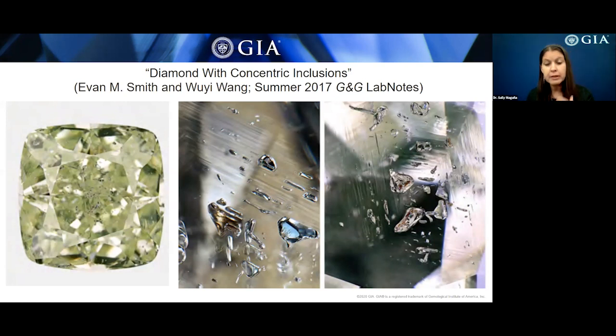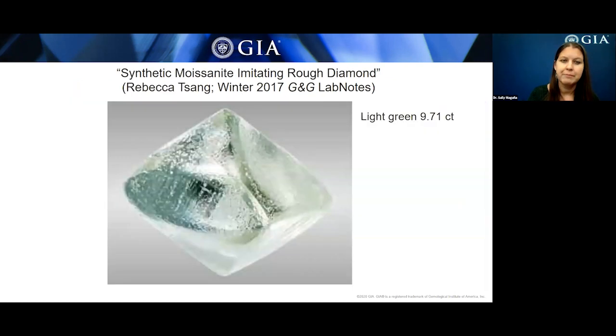Many of the individual inclusions have an elongated or flattened shape that conforms to that growth layering. Thus, both the shape of the individual inclusions and the collective distribution of multiple inclusions imitate that geometry of concentric octahedral diamond growth. This kind of symmetrical growth outlining texture is rarely observed in diamond. So this was a really interesting example of how those inclusions follow that growth layering.